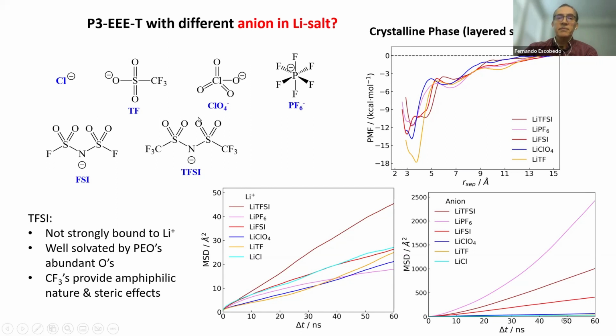so you have a large barrier for dissociation. But also this moiety, if you think about it, is somewhat like an amphiphilic material, right? You have these CF3s that are hydrophobic. So because of that, the system doesn't necessarily stick around long, and it's able to move more easily. You just need a small bias, and this molecule is going to move despite being bulky. So I found it fascinating because, again, initially we didn't understand why this would be the anion of choice. I would think that something smaller would be better, but at least.